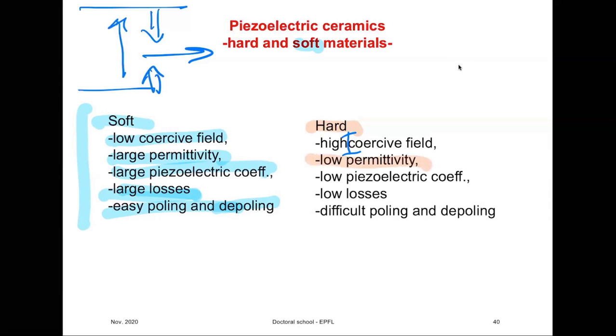They have a lower permittivity than pure materials or soft materials, lower piezoelectric coefficients, lower losses, but somewhat higher conductivity. And they are difficult to pole. You need to pole them for a very long time with, in general, larger fields. And once poled, you will not depole them that easily.